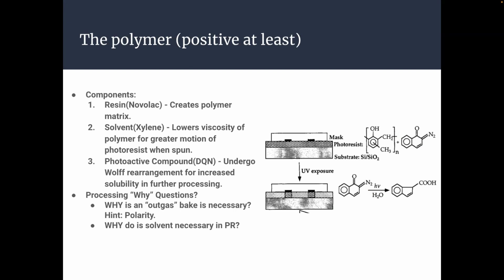This undergoes a Wolff rearrangement. I can detail that right now. If you look at the molecule on the top right, you see that nitrogen. That's pretty stable on its own. With the energy we receive from the light, it gets bounced from the compound, leaving a carbon radical right here. This gets rearranged to a 5-sided ring when the carbon moves up towards the double-bonded oxygen. That carbon and double-bonded oxygen react with water in the atmosphere, leading to a carboxylic acid. That itself is an acid. When you put it in a base, it gets very soluble. The base we use is your actual developer, which you will use after exposing your wafer.